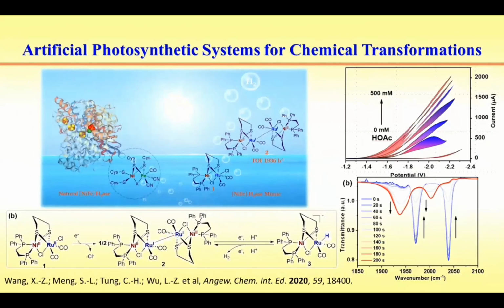Here arises a question. Two electrons are required for one molecule of hydrogen. After the first electron transfer, what is next for the reduced intermediate? To understand the following transformations, we designed a hydrogenase mimic. During the hydrogen evolution, we found a new species in the course of the reaction. The experiment and the DFT calculation demonstrated that this new species is a dimer structure.